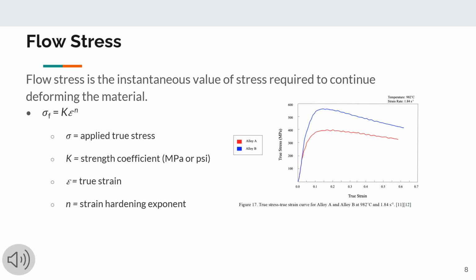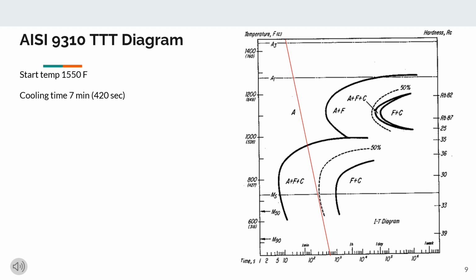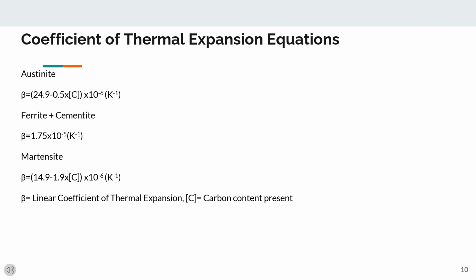The limitations of the TMA apparatus being used being unable to replicate the cooling conditions of our sponsor, we went with a more mathematical approach. Shown here is the time temperature transformation diagram of the steel we are using mapped to the 7-minute cooling. Using the equations shown here, we were able to calculate the coefficient of thermal expansion for each of the transformations that occur in the steel as it begins to cool.